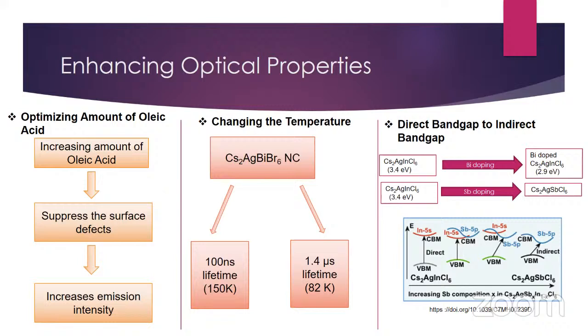Also, by decreasing the temperature, the lifetime of the excited state can be increased. So at low temperature, the amount of trap state decreases, and for that the lifetime increases. So here you can see for the Cs2AgBiBr6 double halide perovskite, when the temperature is high, the lifetime of the excited state is less, and when the temperature is low, the lifetime of the excited state is high.